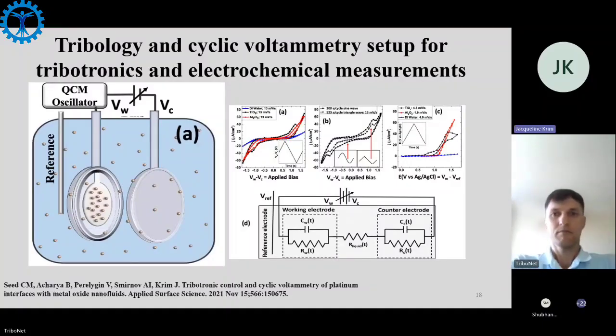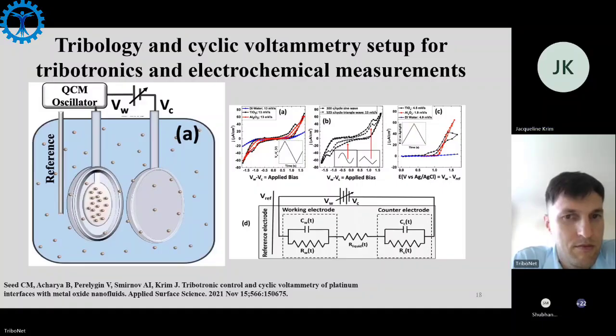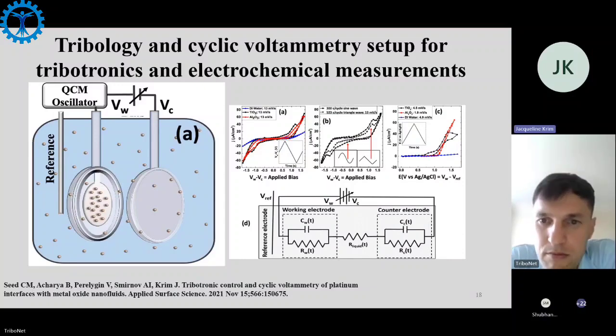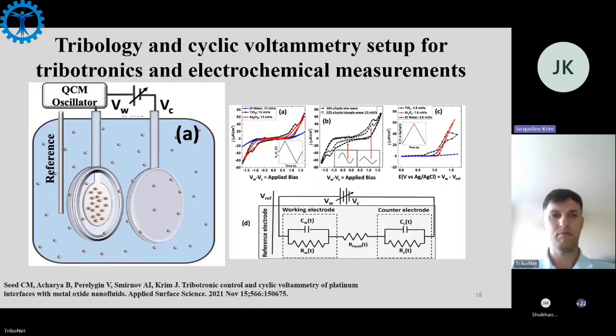Okay, next slide. This is the setup. I'll be showing you some of the results from today, where we performed a tribotronic study of nanofluids sliding on different metal surfaces of a quartz microbalance, put in a reference electrode so that we could also study the electrochemical properties on the surface of the quartz microbalance. And then we changed the voltage between these two parallel plates. So we have a very well-defined field on that surface. We have a quartz crystal microbalance measuring the interfacial friction at one of the contacts. It's nice because we don't just have the collective impact of two contacts touching. We actually know what's going on one contact or the other. And the electrochemical reference is telling us about energy storage and hysteresis.